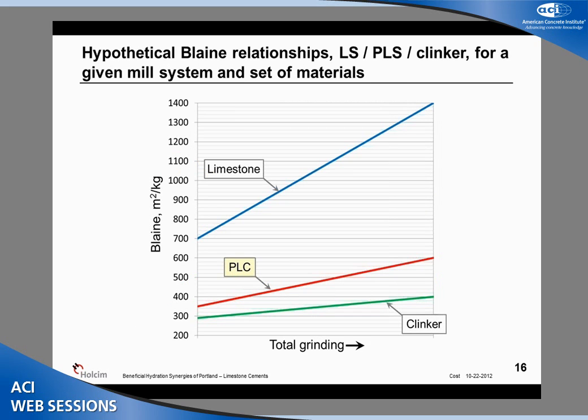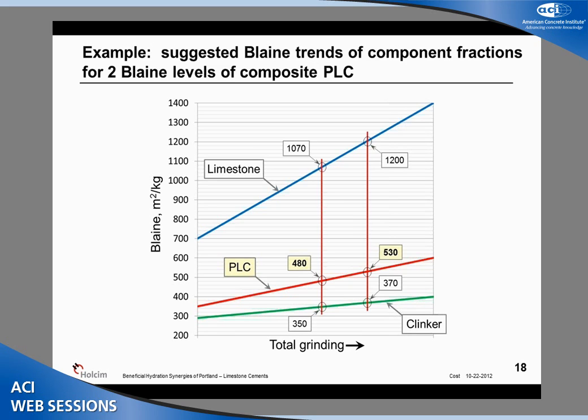So what does this mean in the grand scheme? Well, we think this is kind of a shoot-from-the-hip depiction of what's going on as we increase the grinding time in the mill. This is kind of an educated guess. We've not been able to come up with a good test method for evaluating the different proportions of the finished product. But if this is roughly true, then here would be a couple of examples about the fineness of the component materials of the Portland limestone cement.